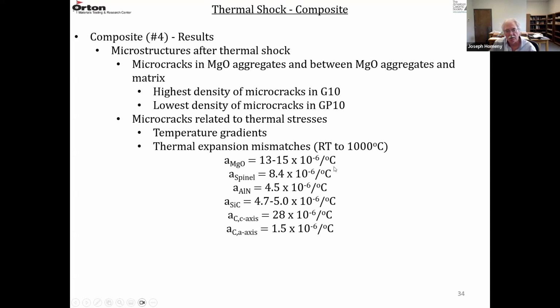So these are thermal expansion coefficients from room temperature to 1,000 degrees C for the different components. This is the linear thermal expansion for MgO, and it's pretty high, 13 to 15 times 10 to the minus 6 per degree C. A minor component, spinel, was 8.4, let's say, times 10 to the minus 6. Another minor component, aluminum nitride, is pretty low. It's a nitride, 4.5 times 10 to the minus 6. And the silicon carbide is also pretty low, 4.7 to about 5 times 10 to the minus 6. So the nitrides and carbides are about half of the spinel and about a third of the MgO.